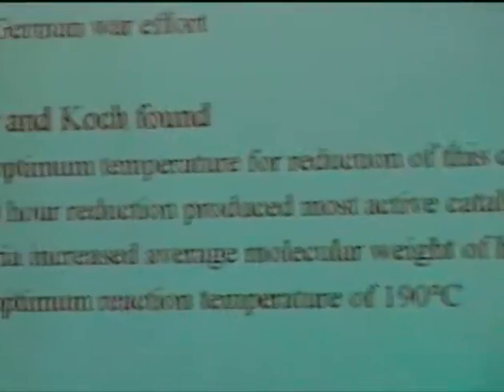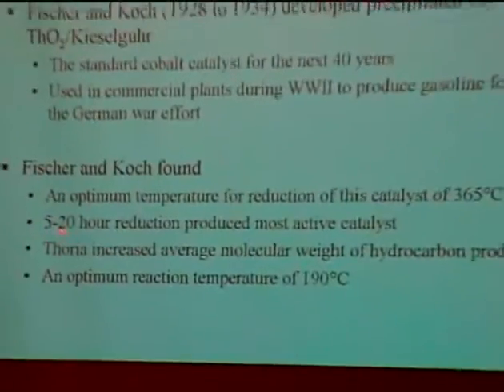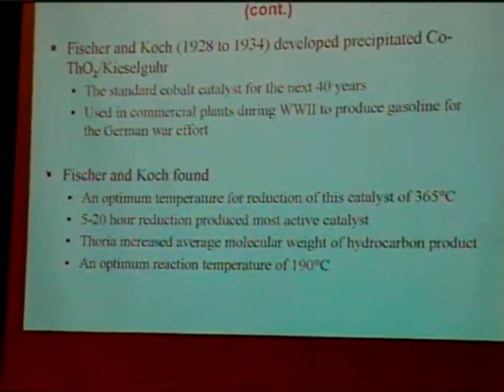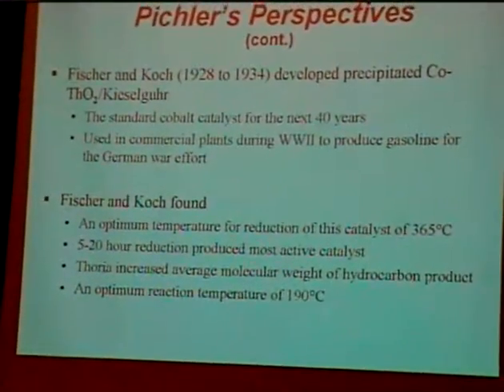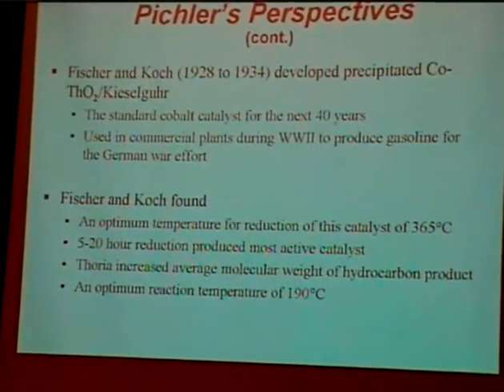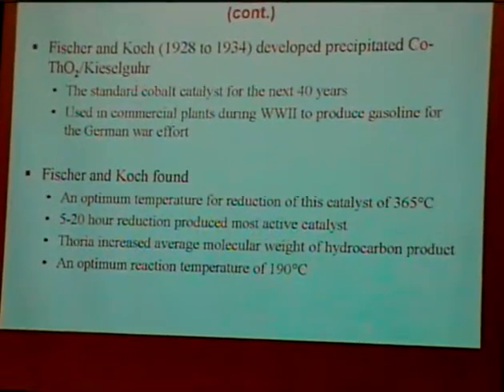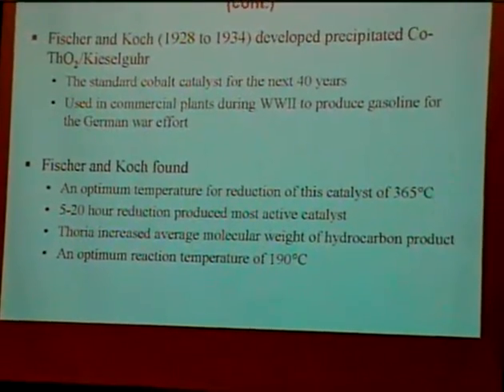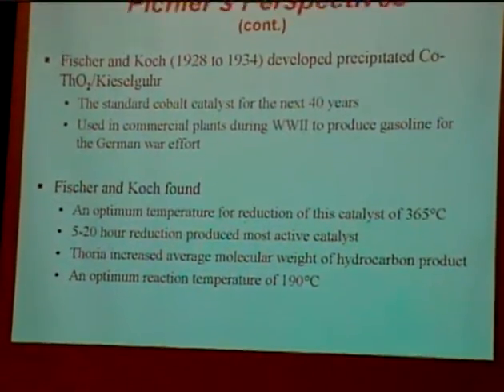Fischer and Koch found an optimum temperature for reduction of the catalyst of about 365 degrees centigrade. 5 to 20 hours reduction produced the most active catalyst. Thoria increased the average molecular weight of the hydrocarbon product, and the optimum temperature for reaction was about 190 degrees.